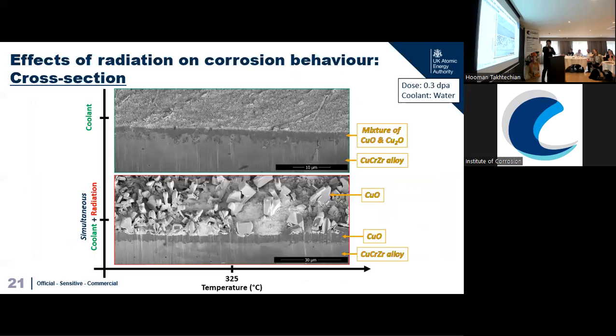One thing I need to draw your attention to is that this is the same region I just showed you, but this is a cross section of the material itself. What you see at the top is the corroded copper surface exposed to just coolant, and you can see this darker contrast is copper oxide, and then you can see the dendritic structure going inwards into the material. And for the region exposed to radiation as well, you can start seeing outgrowth oxide. What it means is that you are increasing the activity of losing material under radiation, and at the same time, the material also corrodes inward.